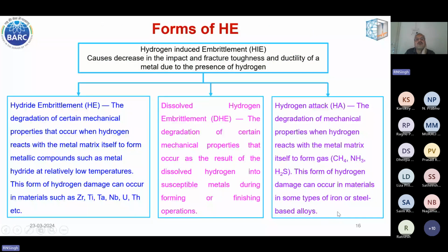So various forms of hydrogen embrittlement have been reported in literature. I have just considered only 3 of them. First one is hydride embrittlement, second is dissolved hydrogen embrittlement, and third one is hydrogen attack. Hydride embrittlement is caused by the formation of hydride precipitate. In case of steels, hydrogen embrittlement is caused by the dissolved hydrogen in the matrix. And the third one is hydrogen attack, which occurs during service, where hydrogen can combine with other interstitials under the operating condition, and that can cause embrittlement.